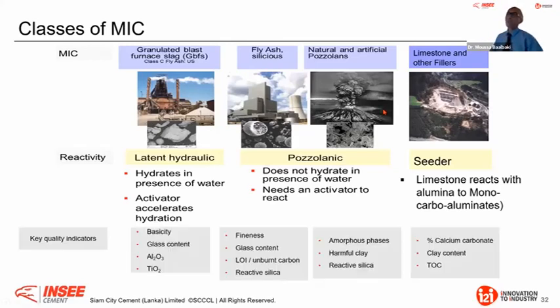Now, of course, when it comes to standards, there are key indicators. Therefore, we know, for example, for the slag, we need to control basicity and the glass content, very important. For example, for slag, we have our internal product specification: more than 90% of glass content, aluminum content, titanium oxide. These are all quality indicators. They are somehow mandatory sometimes, or they are optional. This is really important to take into consideration.